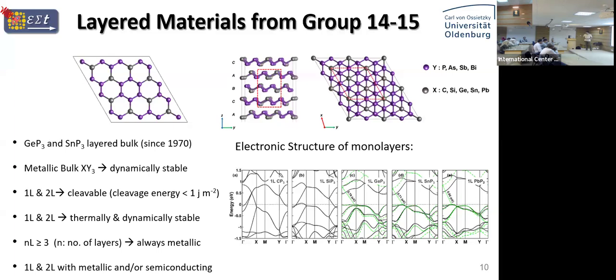So there you don't open the band gap. And in those materials where you see semiconducting, you already see some different colors. So it's essentially the electronic band structure, which shows the size of the electronic band gap and where it is in the reciprocal space. But in the colored shade, you will see that we have opening a much larger band gap. And this is essentially what I highlighted a few slides back, the effective potential that I marked in the red. So based on what you chose, how you approximate that effective potential, you could get a different band gap.